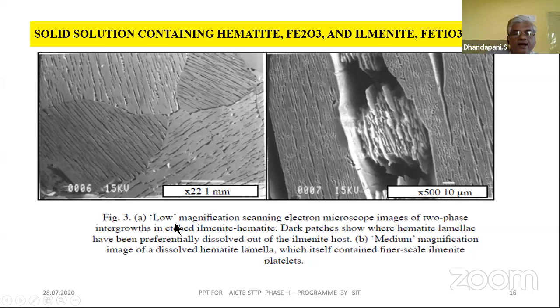First, low magnification, scanning electron microscope, this is SEM analysis, images of a two-phase intergrowth of etched ilmenite and hematite. These are the platelets. Dark patches show where hematite lamellae have been preferentially dissolved out of the ilmenite host, meaning that ilmenite is the main host in which hematite is dissolved. So one is the solvent, and like that hematite is dissolved. These black lines are hematite.